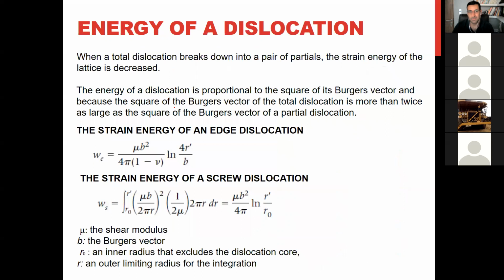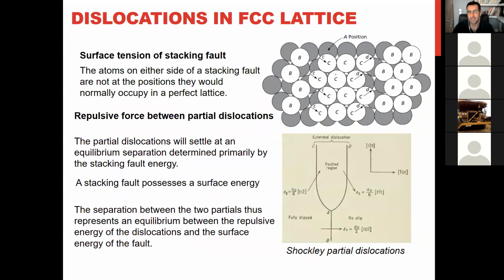To be familiar with this, it's like this. Look, when you have a partial dislocation, it means that this dislocation decomposes into two dislocations. These two dislocations we call partial dislocations. In the case of the FCC lattice, they call them Shockley partial dislocations, and these very easily happen in FCC metals and help the material deform more easily. You will see the position of these atoms compared with this is in a C position, not in B position. So if you have here A, B, C, A, here you have C, A, C. So here we call it a stacking fault.